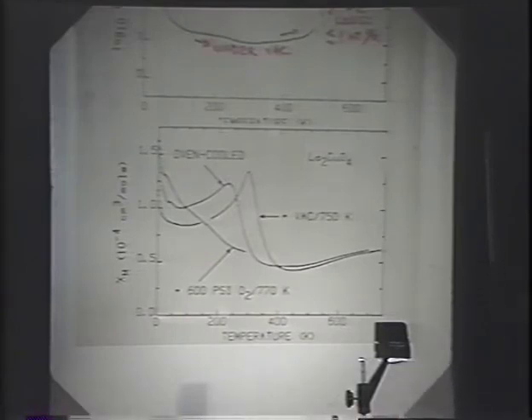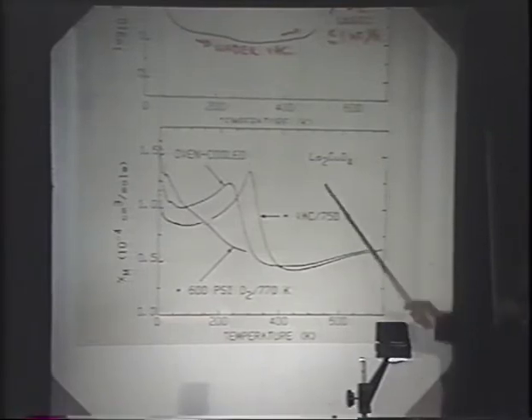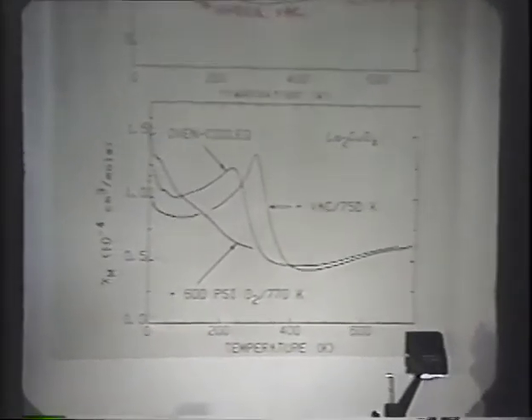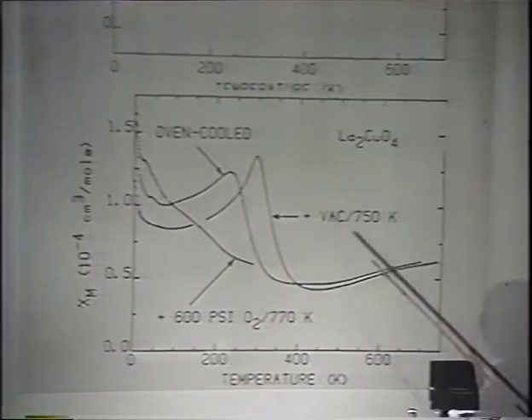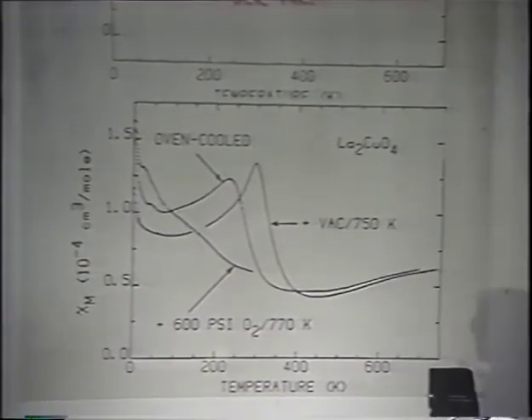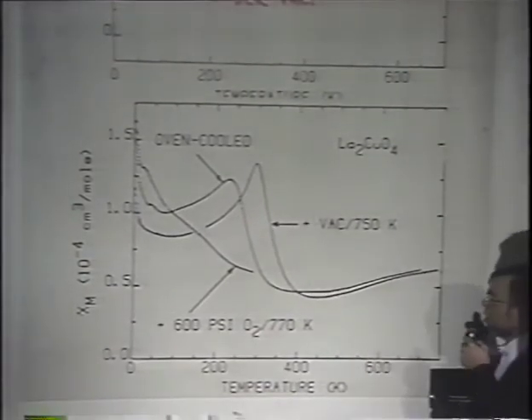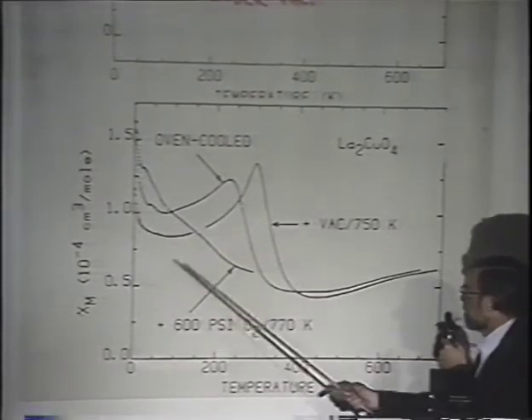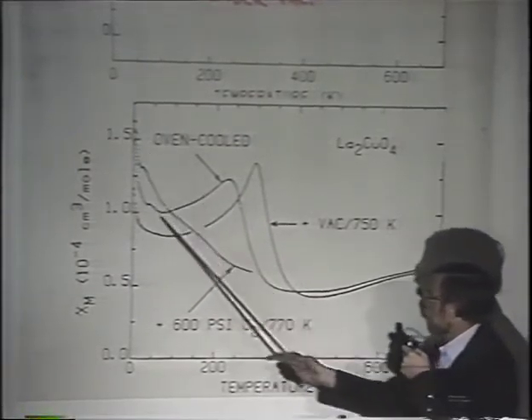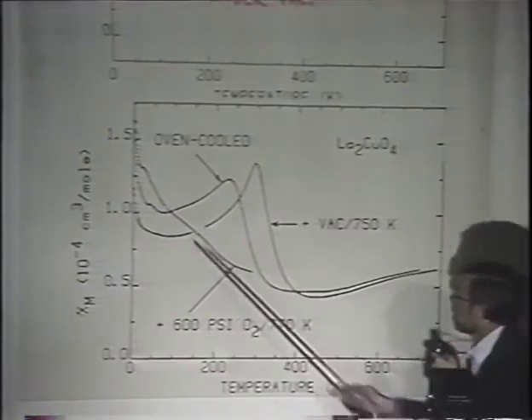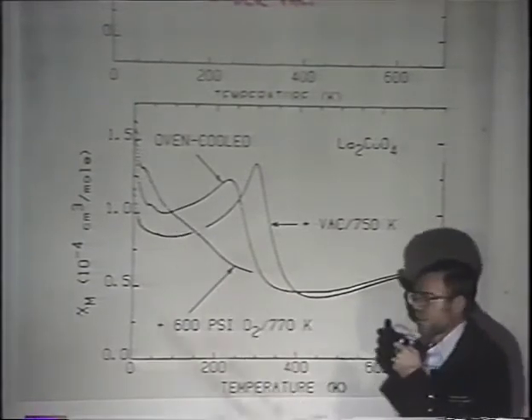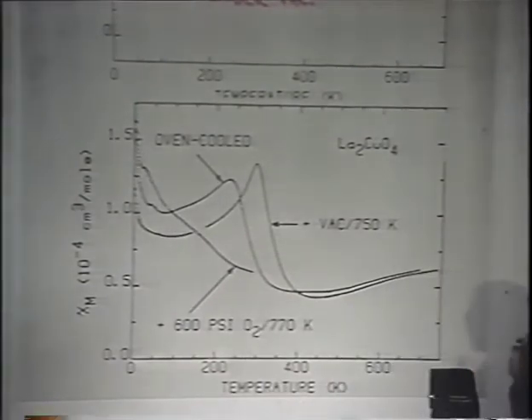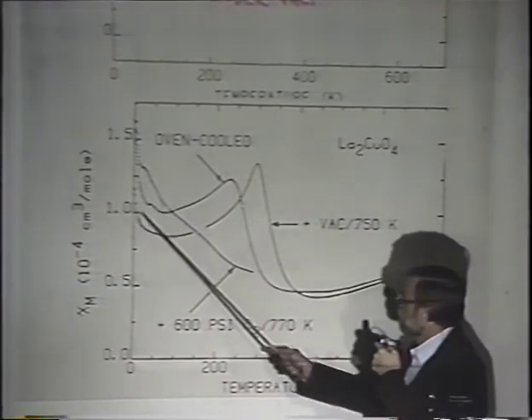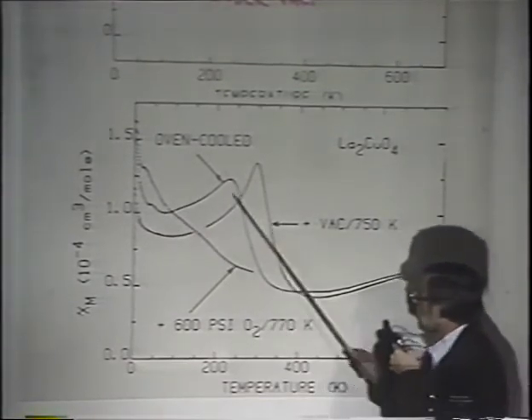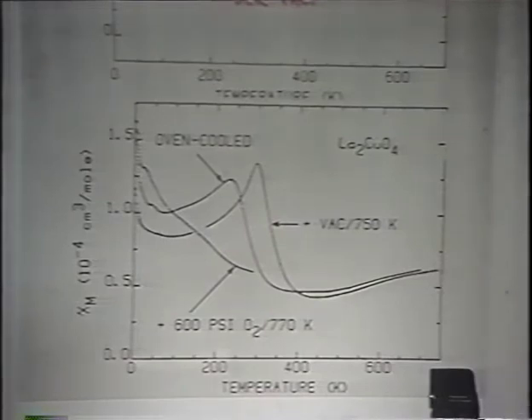In the lower curve, I've plotted the magnetic susceptibility versus temperature for the pure end member treated in various ways. Typically, we turn the oven off and just let the samples cool. When you do that, you get a susceptibility with this kind of behavior. You have a low temperature tail just due to copper 2+ defects. You have a little feature here which we don't understand yet. And then we have what looks like an antiferromagnetic transition.